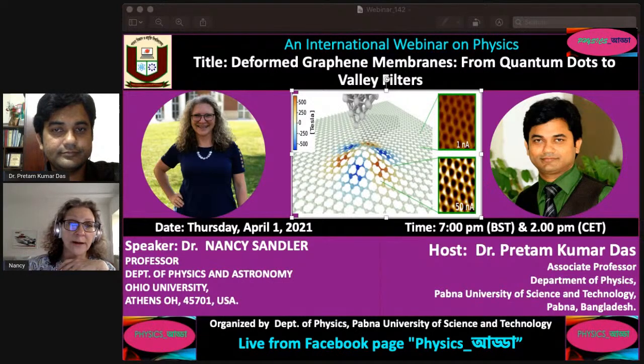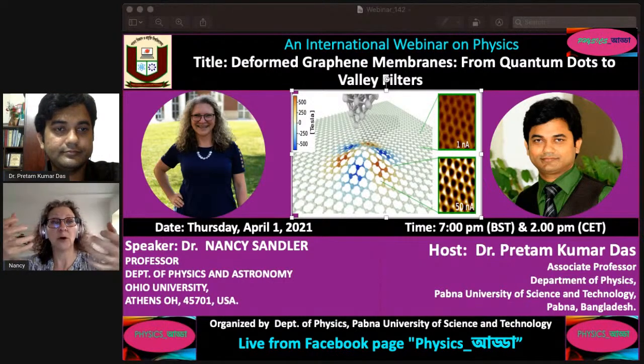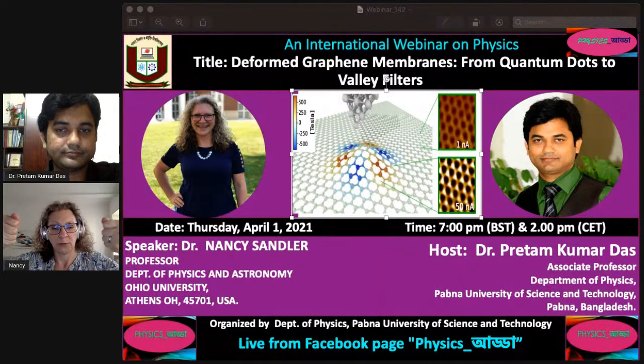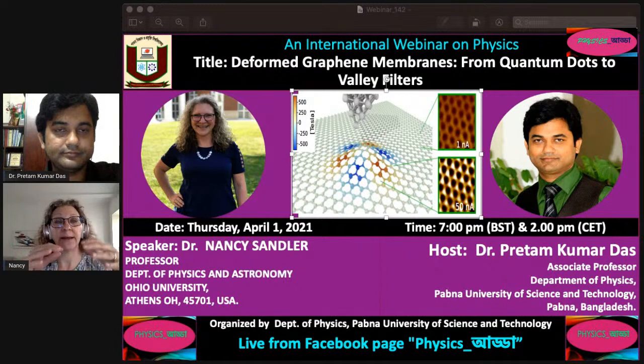Another way to deform graphene is suspending it, grabbing the graphene, attaching it to two contacts and separating the contacts. Another way is to deposit graphene on a material that has been perforated, so graphene is on a hole, and people put gas in the hole and they inflate it and create a bubble. So there are many different ways that we can deform graphene.